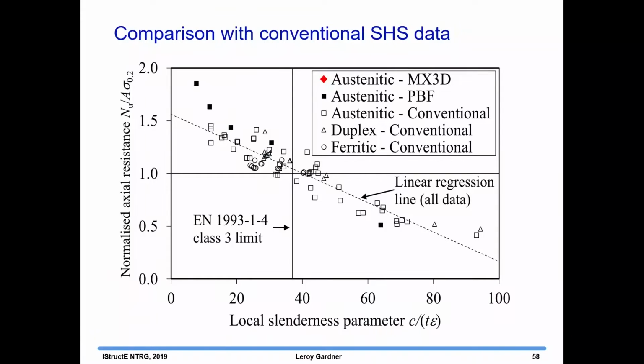And if we look at the normalized resistance, the vertical axis of this graph is the ultimate load we achieved in these compression tests, normalized by the yield load, or squash load, area times yield strength, plotted against the local slenderness of the cross-section. So class 4 sections would be moving towards the right-hand side. And then I've just got some existing test data here, mainly on conventionally produced stainless steel. And you get a reducing normalized capacity with increasing slenderness because local buckling is becoming more pronounced.